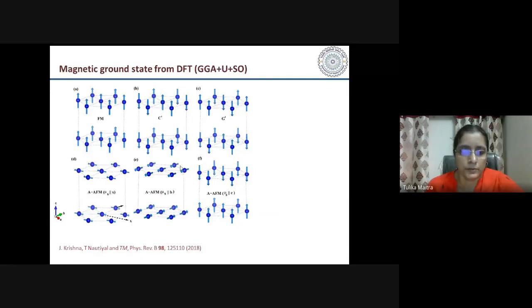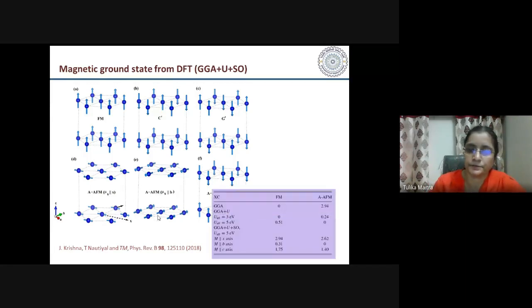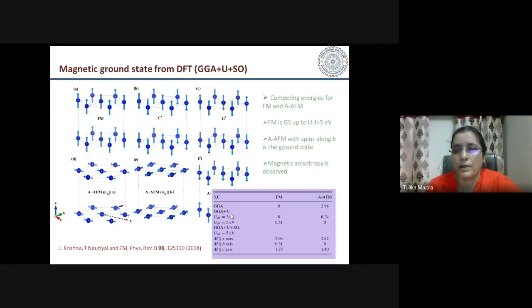Okay. So what we did is we calculated the total energies for various magnetic structures, like ferromagnetic structure, then C prime, G prime, and A-type antiferromagnetic structure, with spin moments pointed along various directions. And what we find here is that there are competing energies for the ferromagnetic and A-type antiferromagnetic states. Though the A-type antiferromagnetic state is the ground state, the ferromagnetic state has a competing energy. The difference is only about 2 to 3 meV, so this ferromagnetic state is very close to the ground state.